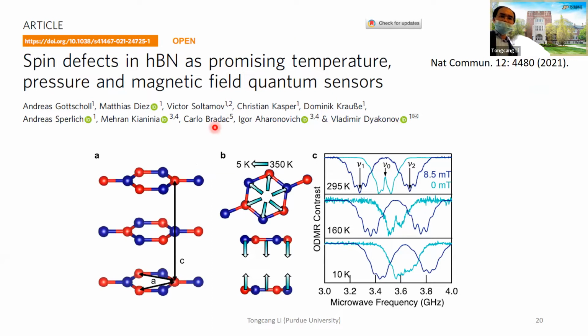They show that, of course, when you change the temperature, the lattice constant will change, so that will change the frequency. And when you add a magnetic field, you will also change the separation, right? So when you change the temperature from 0 Kelvin to room temperature, the center shifts to a smaller frequency as the temperature increases.